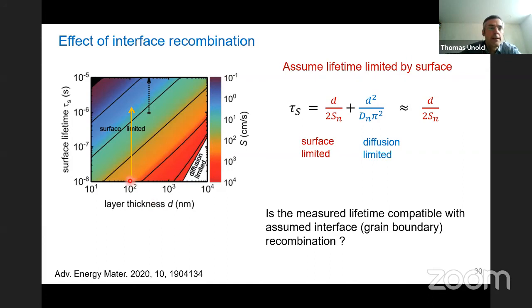So let's say that grains are 100 nanometer thick. So this would be this line here. And now depending on what you measure, if you measure here 10 nanoseconds, if I'm right, and then you look at the color code, then it could be that your grain boundaries have 100 centimeter per second recombination velocity. But if you measure again this microsecond here, then your grain boundaries basically have a recombination velocity of one, which is very low.